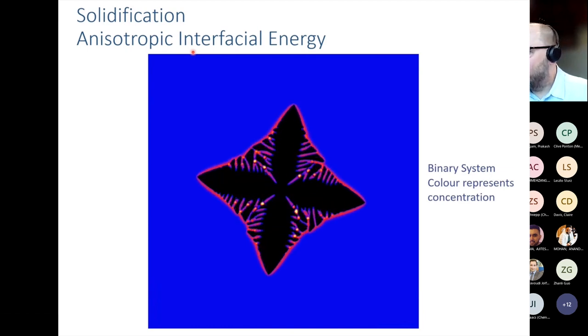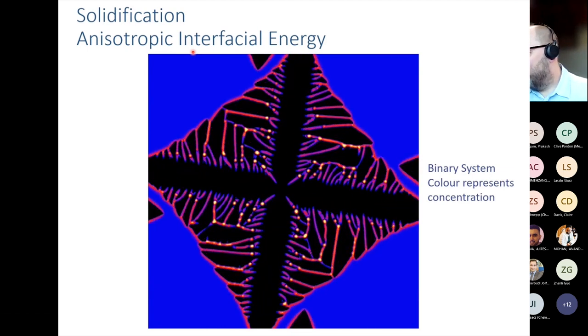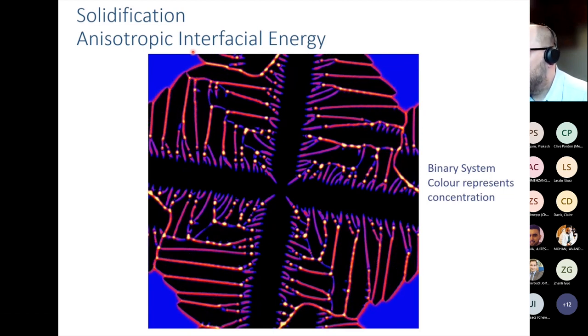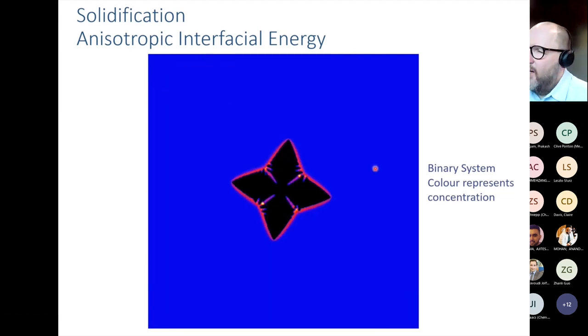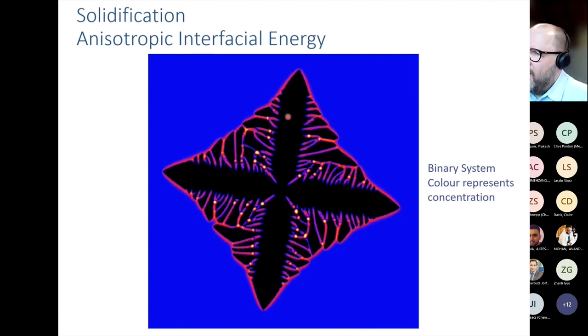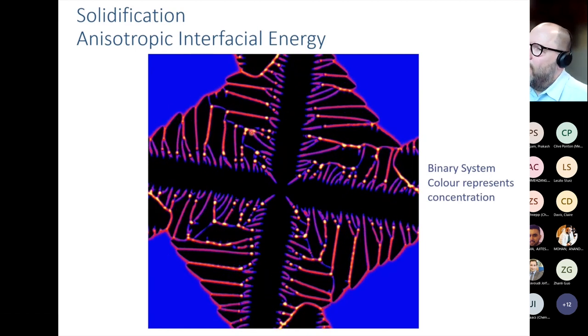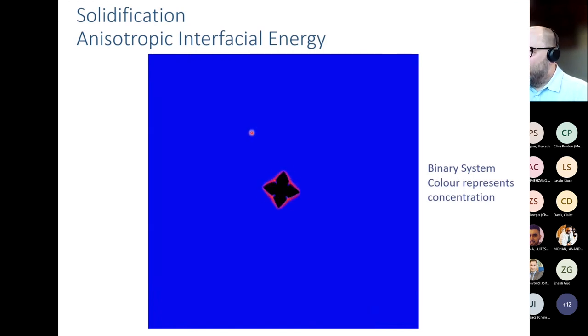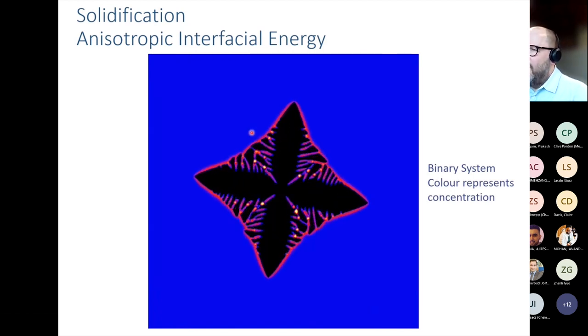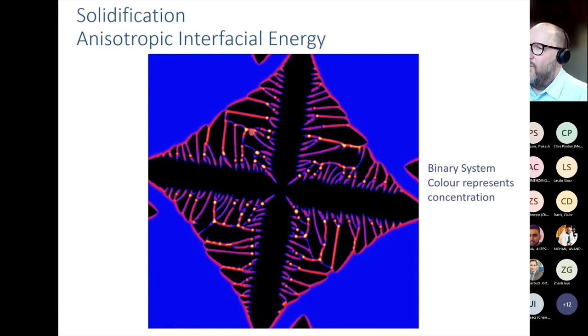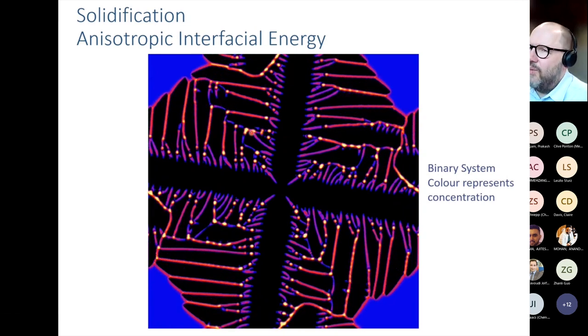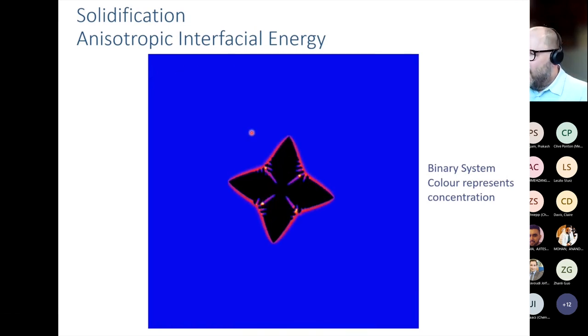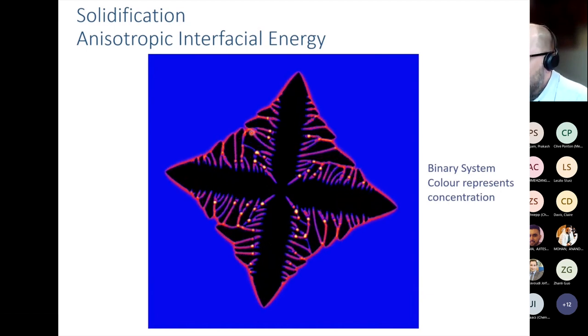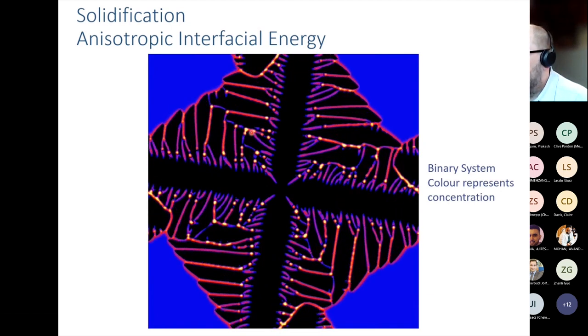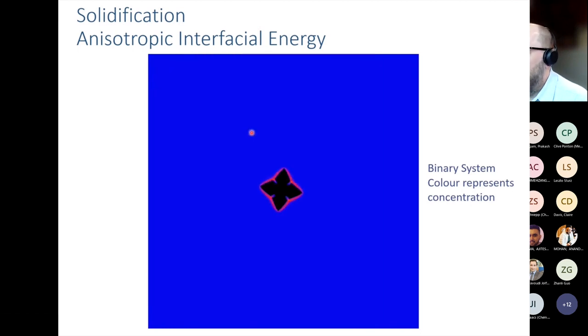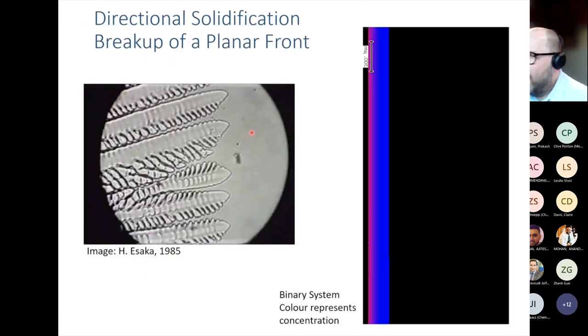Suddenly we get a dendrite. These are the dendrites we've seen from solidification science over and over again, showing preferred growth direction, aligning to the 100 direction, forming side arms, which then again grow along 100. But apart from that, showing the same segregation pattern, like a slight pileup, and the deep channels, which absorb some of the highly enriched liquid. So we have a tool that can actually capture quite a lot of effects already. Okay. So what are we getting if we apply this to different situations?